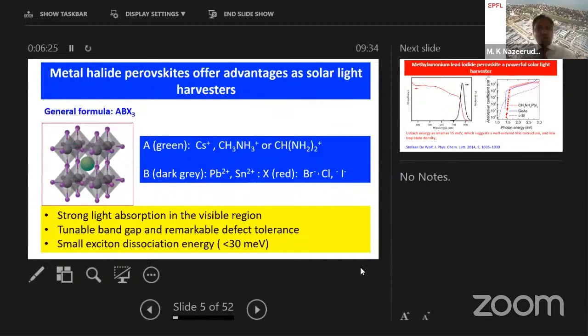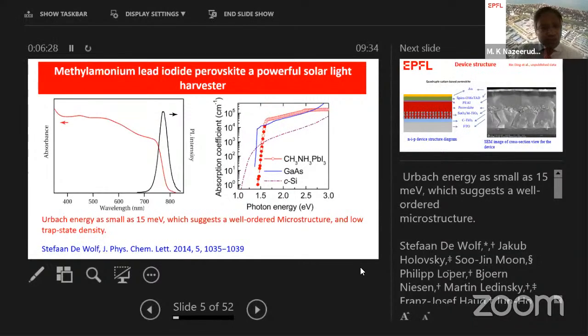So the next slide shows you the spectral properties of this material. As we discussed in the previous slide, it absorbs the whole visible spectrum starting from 400 nanometers up to 800 nanometers, as described in this red curve. And wherever you excite this material, you have a very strong emission. Another interesting property is shown on the right side. You have a very sharp onset, and this sharp onset suggests that the Urbach energy is very small, 15 milli-electron volts, and a well-ordered microstructure. And this particular property is being used for tandem solar cells. You will see in a couple of slides what tandem solar cells are.